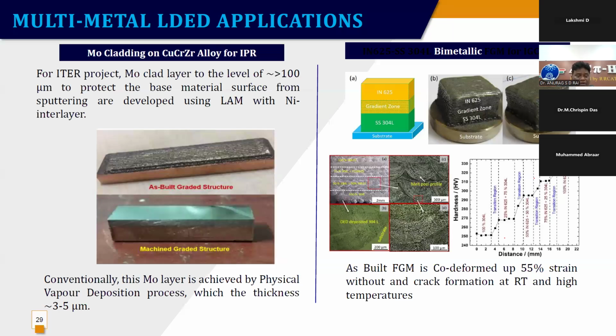There was a requirement from the Institute of Plasma Research to build some component for ITER. India ITER, you know, the International Thermonuclear Experimental Reactor that we are building in France, to demonstrate nuclear fusion technology. So in one of their components, they wanted a 100 micron moly on the copper, and this copper is basically a copper chromium zirconium alloy. And the idea here is, if you have moly on the front, and then you have a plasma inside, the erosion of the material will be less, and that was done.